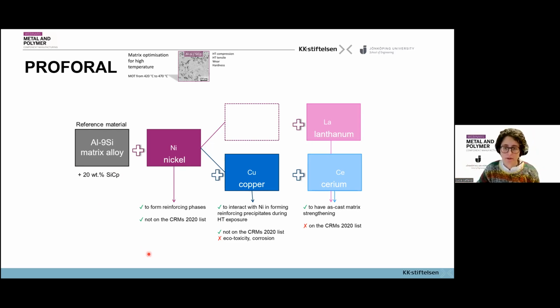material at elevated temperature. So we started with nickel, which is a well-known element to be added to aluminum silicon alloys to form nickel-based reinforcing phases that are stable at high temperature. And also nickel is not on the critical raw material list of 2020 that the European Commission issued. Then we also looked into copper, because it is also known to interact with nickel in forming reinforcing precipitates during high temperature exposure. So the thinking was to have another mechanism of reinforcement that might be active throughout the life of the brake disc itself.